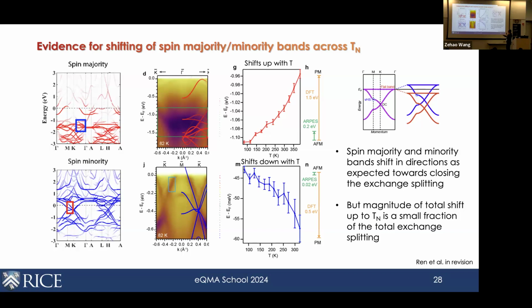So in that way, we understand these are indeed the spin majority and spin minority states, and then we can look carefully at how they evolve as a function of temperature. You see here they are evolving in energy, but if I plot the total amount in energy that they have shifted, that's the green stuff here, compared to the exchange splitting for that band calculated by DFT, I hope you can see that the amount of shift that happens across the ordering temperature is a small fraction of the actual exchange splitting from DFT. So in essence, this suggests that for iron tin, the magnetism should be largely local in nature, as opposed to the itinerant Stoner picture, right?